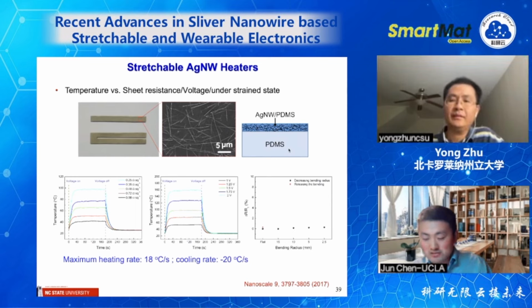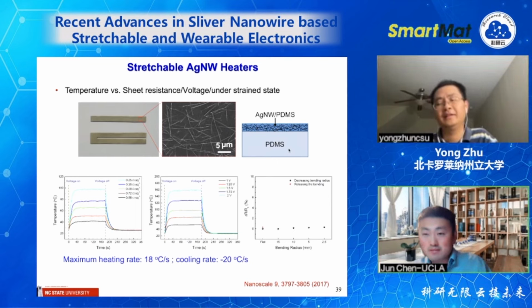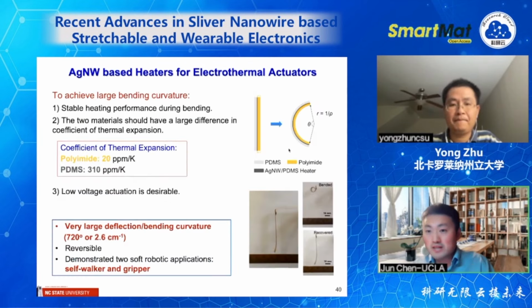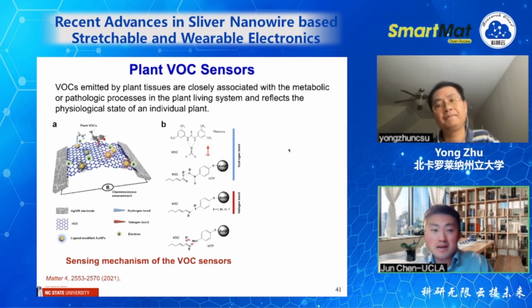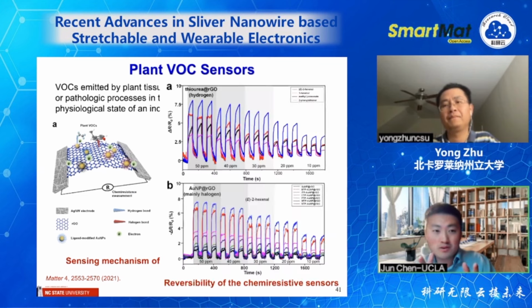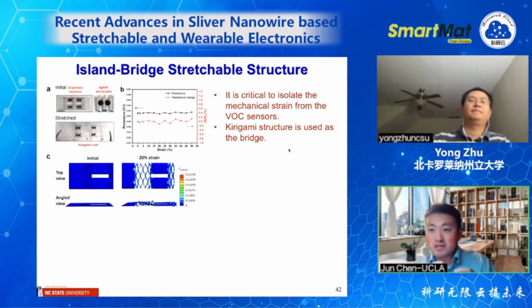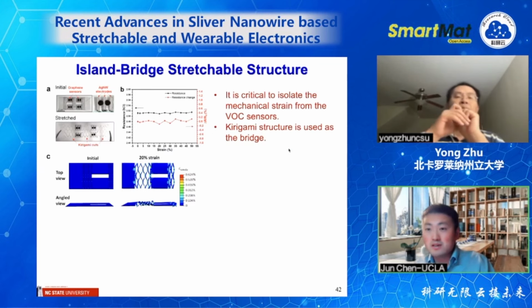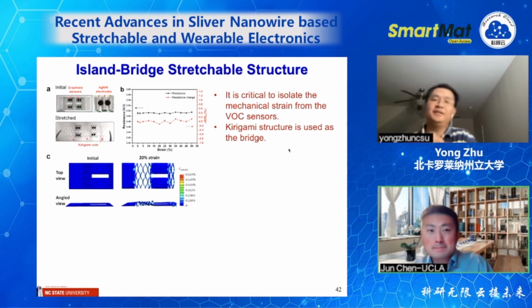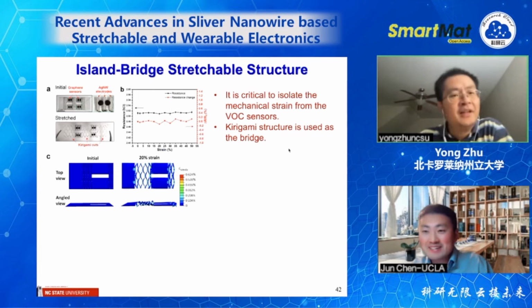Okay, great. There's one last question. They have a concern about the VOC sensor. You're using the silver nanowire composite as electrodes to contact the graphene on the substrate. How can you make sure the contact resistance between the graphene and the silver nanowire composite is consistent for each individual device? Okay, very good question. All these are good questions.